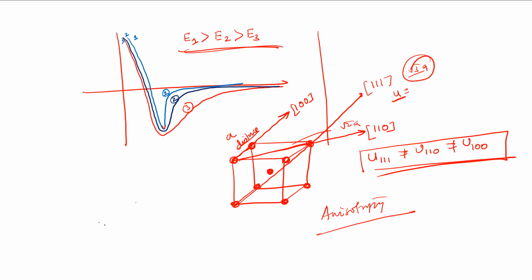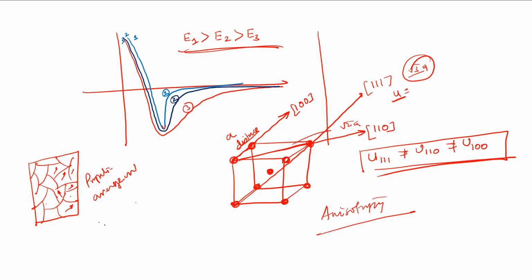So that's why, see, when we have a very big material and we have many grains, right? When we have many grains, then what happens, each grain will show some anisotropy, but effectively, suppose this is the anisotropy from other grain, but effectively if you combine all the grains, then the properties get averaged out, right? That's why we get a common property when we have multi-grain material, right?